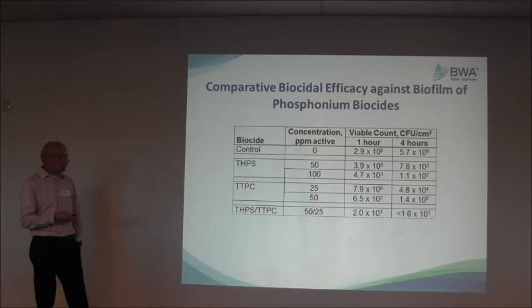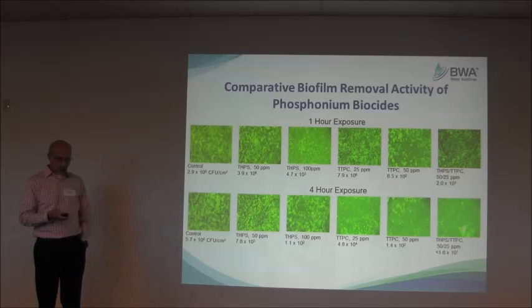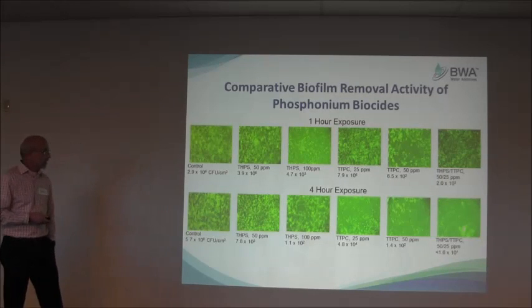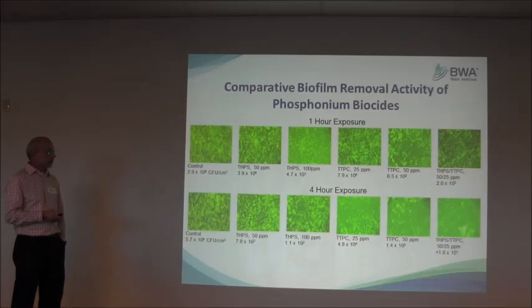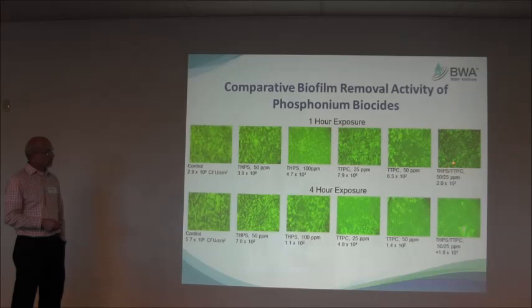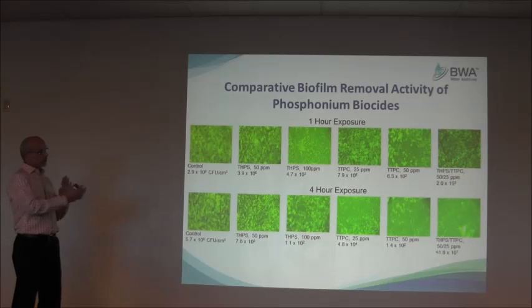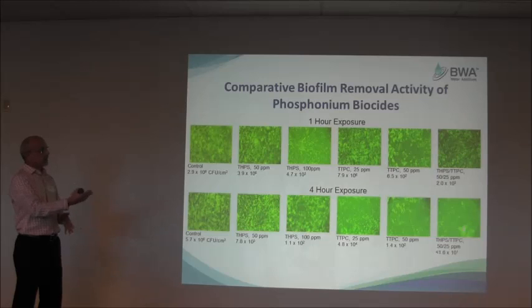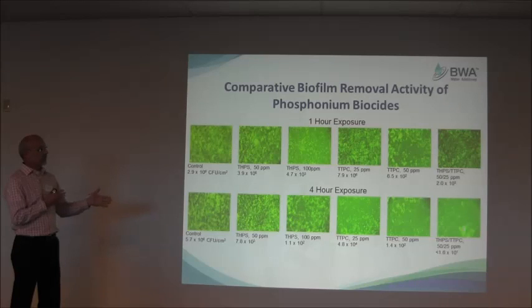We were encouraged by this result, and looking at the biofilm removal, we do see very good results with the combination — even slightly better than TTPC by itself at 50 ppm. You're able to reduce the concentration of these biocides by half and still get as good activity as the individual products at higher dosage.